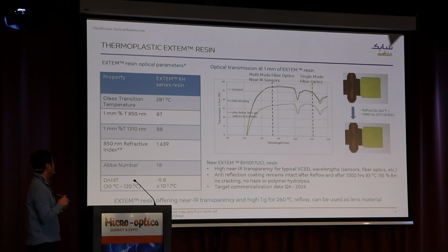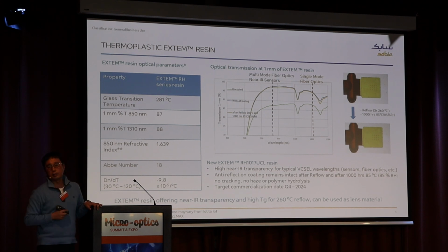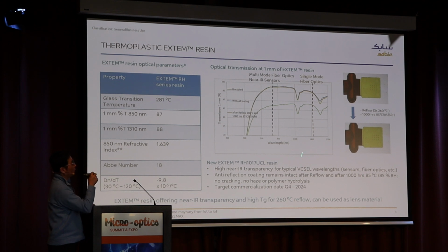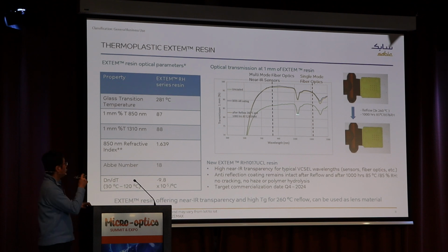So here we have some material properties, like light transmission at different wavelengths, refractive index. But of course, you don't need to remember. If you need more data, we can provide optical constants. Also, these optical constants are already included in either ANSYS Zemax or COMSOL, so you can simply upload the material library. On the right-hand side, we plot the light transmission with respect to the wavelengths. So, spectral transmission. Here we emphasize the two typical wavelengths. At 850, this is quite often used in multimode fiber optics, also near IR sensors. Another point, at 1310, is quite often used for single mode fiber optics. As you can see, we have around 87–88% transmission at 1 millimeter without any AR coating.